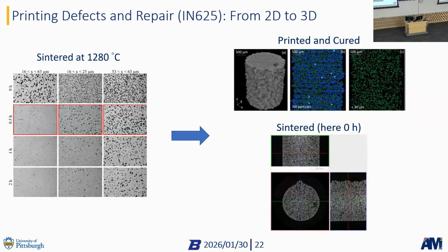So you saw on these previous pictures, if you looked really closely, that there were lines in some of them, right? So these are print defects. If you have a powder, especially a light powder, smaller powder size, maybe lower density powder, then you imprint defects in each layer, right? And we wanted to see, is this actually something that is real, or is this just a defect maybe in the 2D microstructure? So we did microcomputed tomography and saw that no, this is actually real. It's throughout the structure, and this can be a problem, right? If we need to print small particle powder or light powder, then we need to fix this.